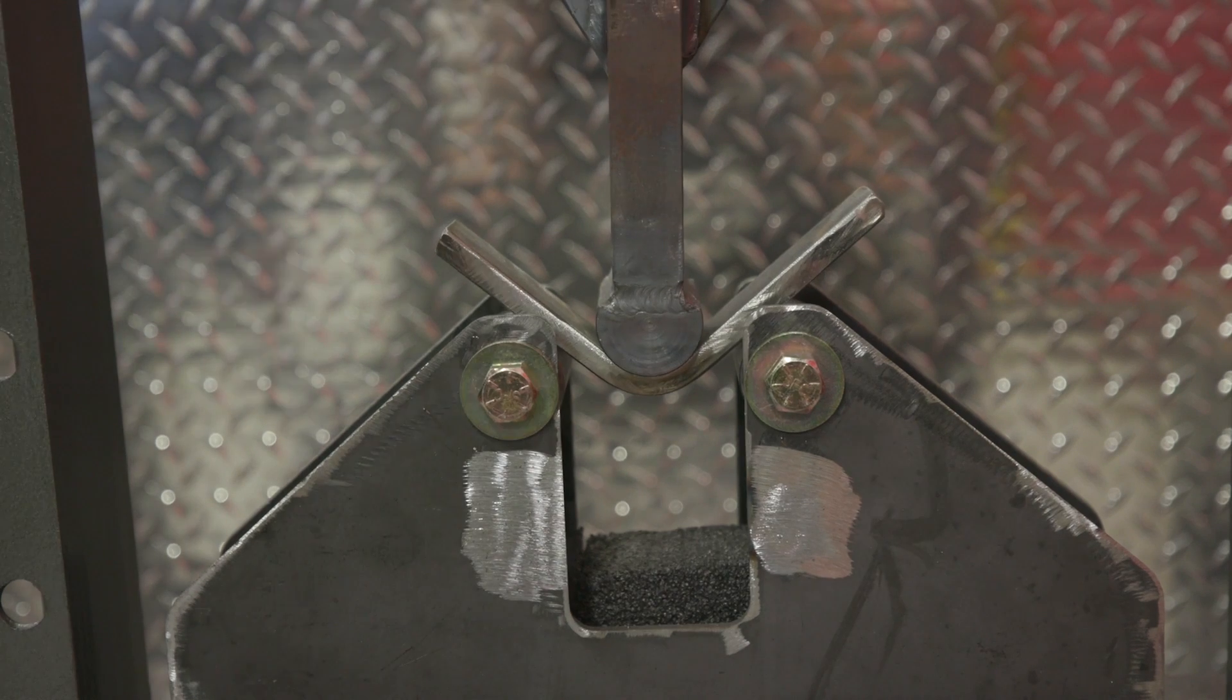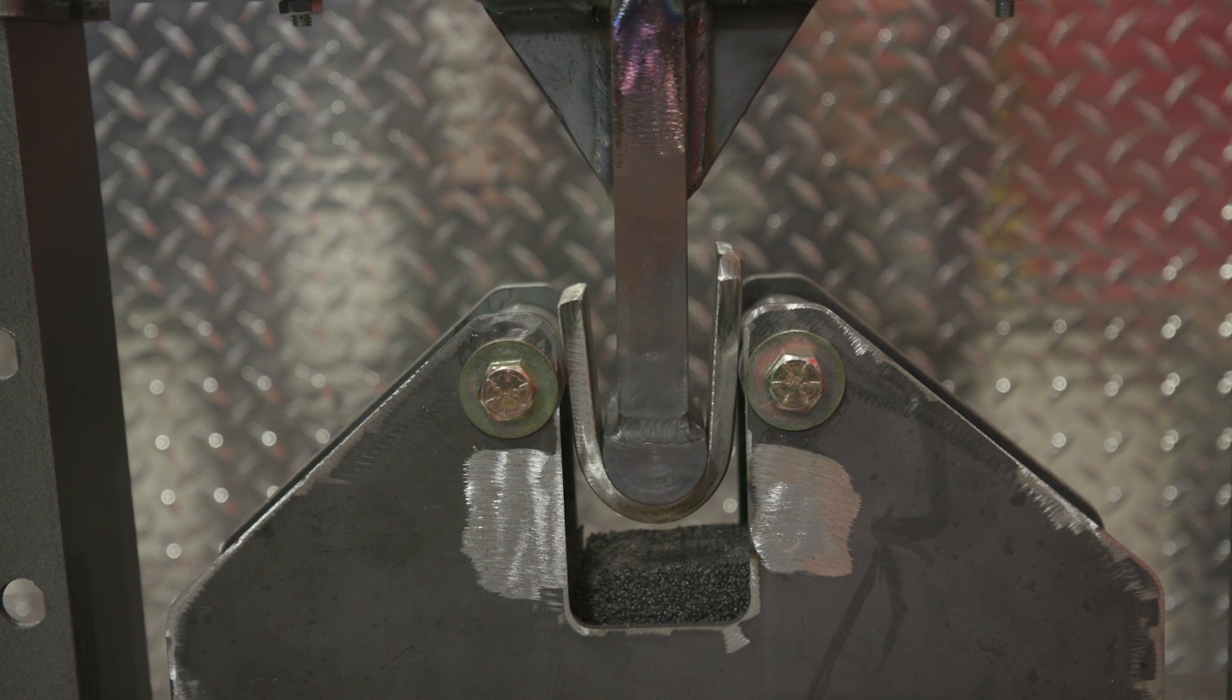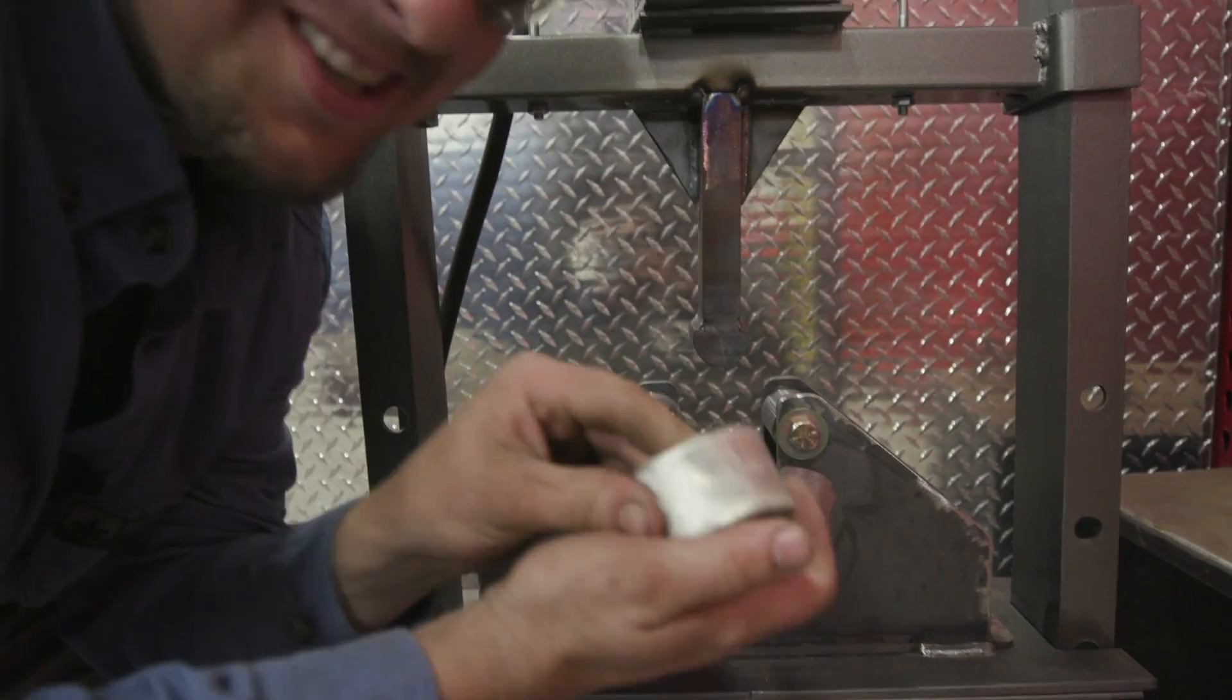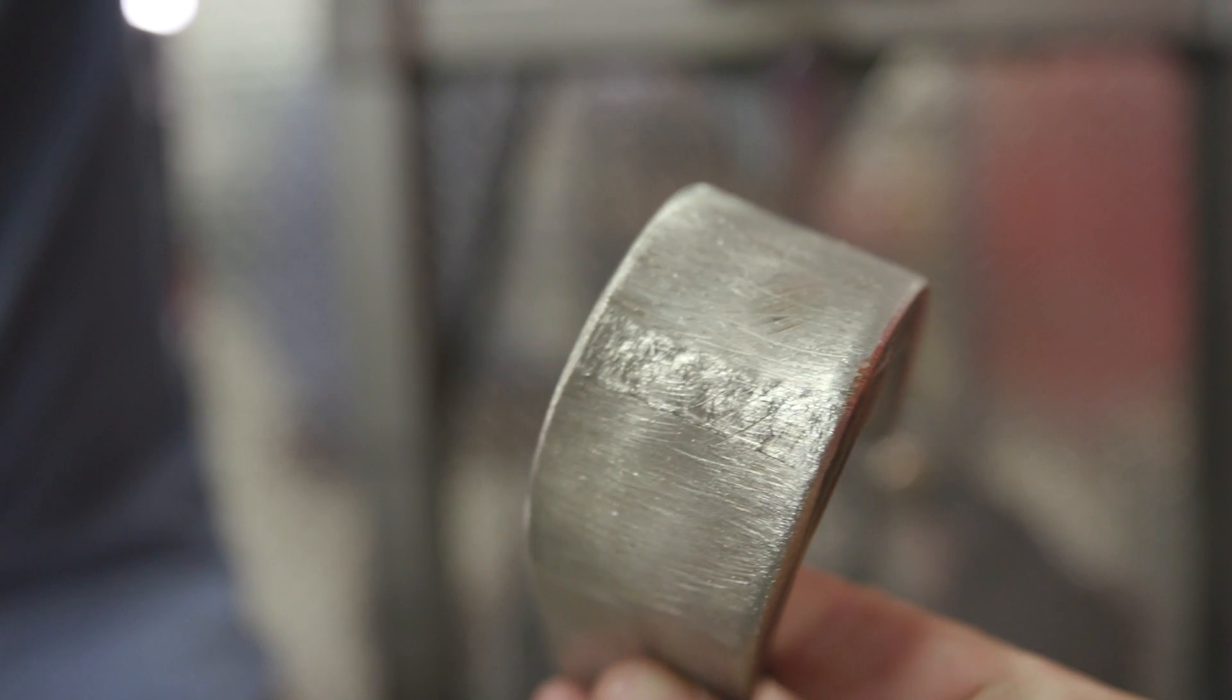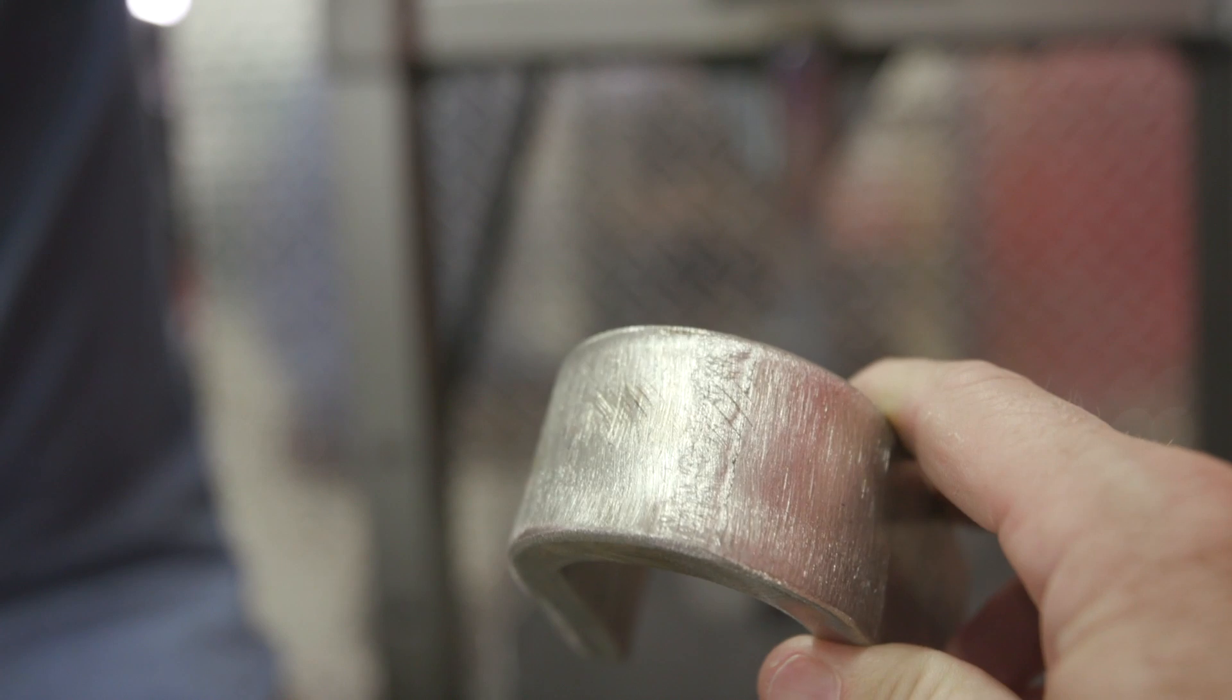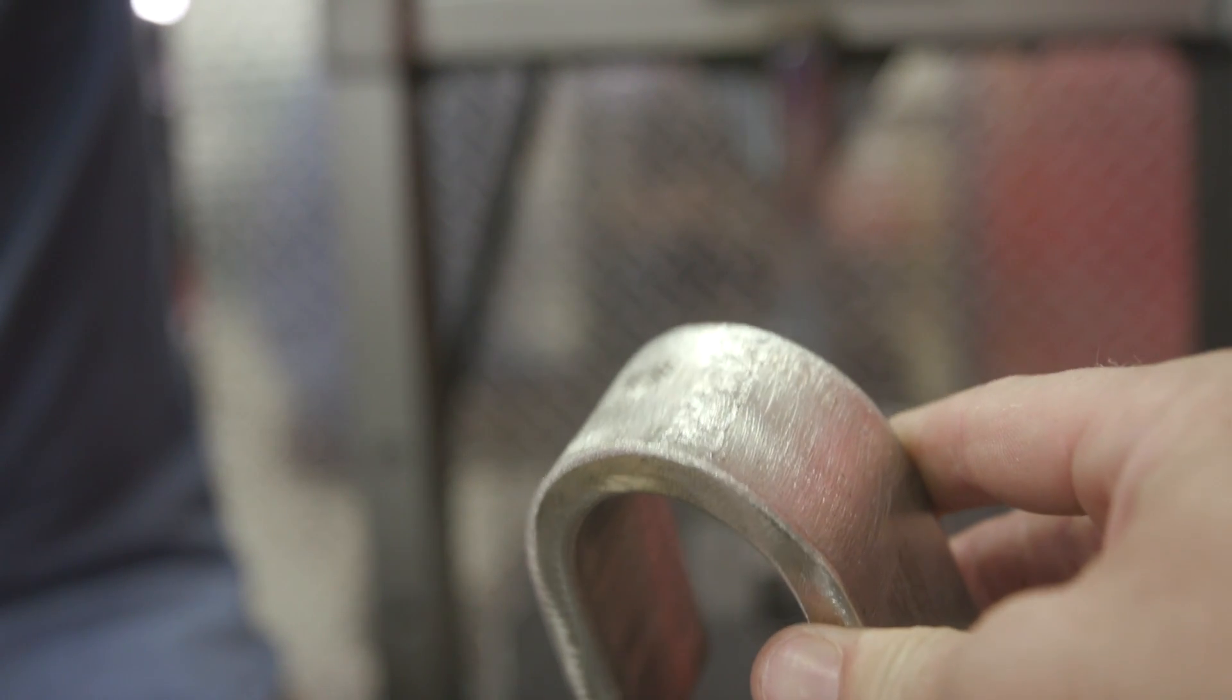It looks okay so far, but we'll see. Right about now is where it's getting pressure at. I'm going to go all the way down. What do you guys think? Huh? Oh, it fell. Sorry. I can't believe that passed. This is just a random thought right here we had earlier today. Hey, will this pass? And there's nothing. Look, I'm actually shocked this passed because everyone says you can short circuit. You can weld up to five sixteenths. But the backing strip was only a quarter inch and I turned up my wire feed speed. So we get good penetration. I'm impressed. Böhler wire. I mean, that's good wire then. Look at that.